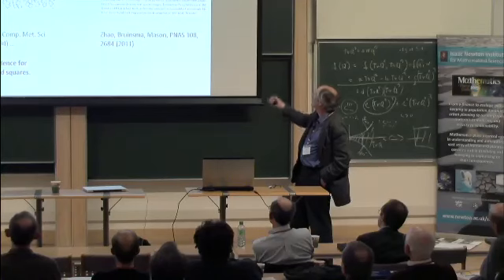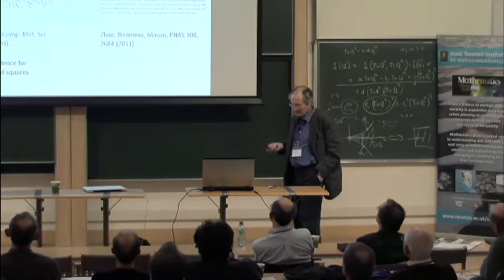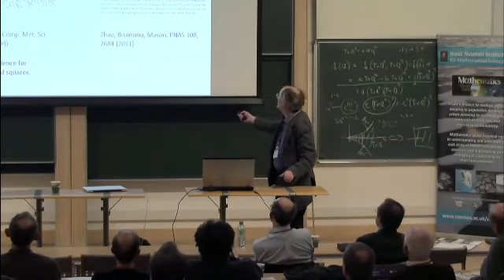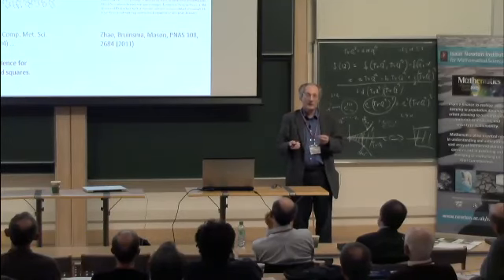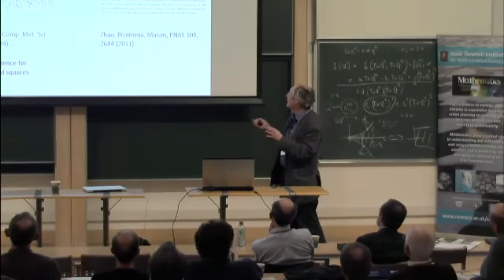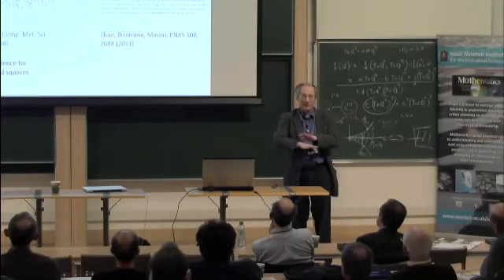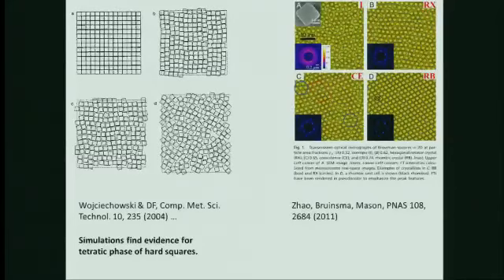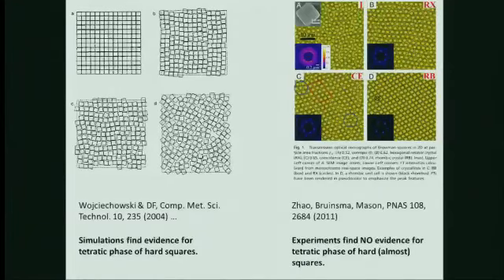But then much more recently, actually last year, Mason's group at UCLA, they can make squares. They have a lithography machine. I don't know whether this was done by lithography, but probably. You just put squares on the surface of an interface, and then you look at the phase behavior. You see that this looks very much like the pictures I was showing: crystal, a bit less crystalline, much less crystalline, etc. And they looked for a possible tetratic phase, and they said, no, there's none. So you say, oh, so maybe there was something wrong in these simulations after all. They were too small, I don't know.